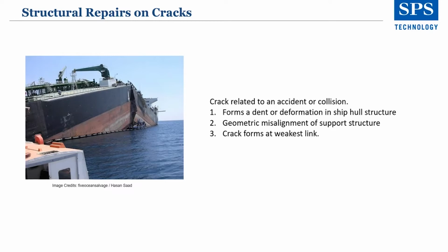When a crack is found in a ship structure during a routine inspection, or in some cases by chance from a keen-eyed marine engineer on their rounds, the first thought is, what caused the crack? Is this the only one in the area? Is the day-to-day operation of the ship contributing to the cause of the crack? And what do we do to address the crack? We need to stop it growing, and we need to identify a suitable repair method so the same crack doesn't reappear after the repair has been completed.